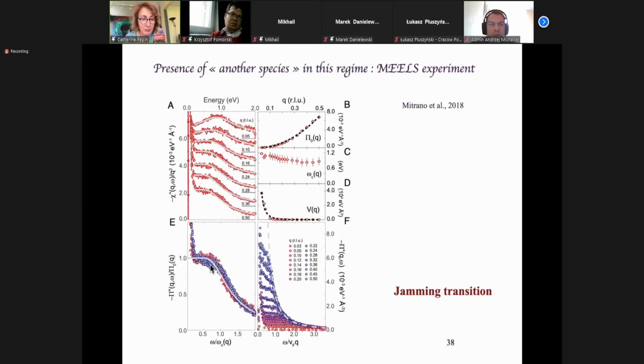And see, this is compressibility. So it's Mitrano's experiment with compressibility over there. And you see a plateau, but the size of the plateau, if you look at this omega here, is very close to 0.8, 0.9 electron volt. Namely, it's the size of a strong Coulomb repulsion on site of roughly 1 electron volt.